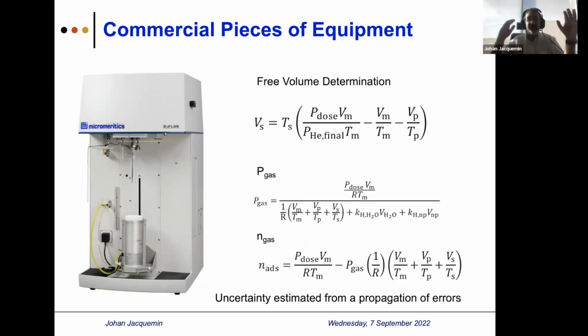And basically what they recommend is to determine the free volume, and then, of course, they determine the volume of the manifold, the volume of the solid sample pore, and they record the temperature at this particular place. And thanks to expansion measurement, I would say, they determine the volume of the cell. Of course, the pressure of the gas will depend in this technique on the dose that you add, because you are working with helium, and then we can add micro sampling, I would say, of some gas